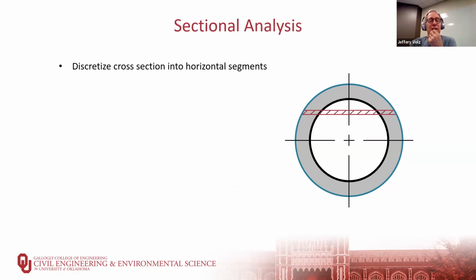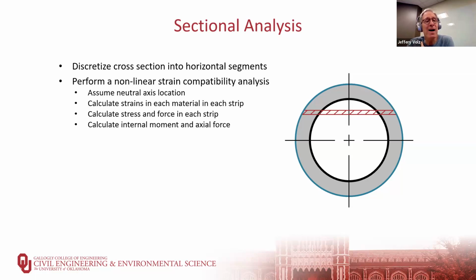So then we would do a sectional analysis, which is very similar to how we analyze reinforced concrete columns or steel composite columns. We discretize or segment the cross-section into a series of strips. Because it's a circular column, you need smaller strips than if it was a rectangular or square column. And then we perform a nonlinear strain compatibility analysis, which is exactly what we do for reinforced concrete. We assume a neutral axis location, and then based on plane sections remaining plane, the Navier-Bernoulli beam theory, we can calculate the strains at each level, at each layer, based on its distance from the neutral axis, because the strain diagram is simply linear. Once you have those strains, you go to the stress strain diagram for the concrete and the steel and calculate the resultant stress.